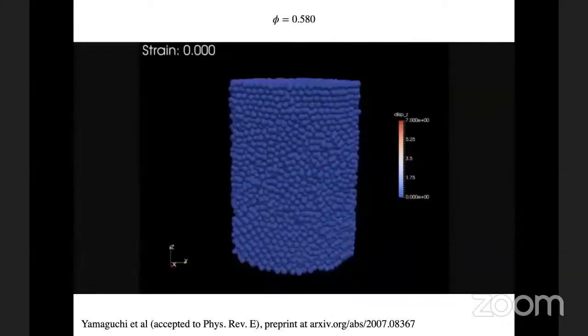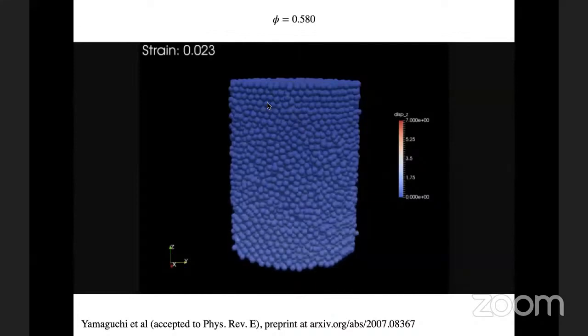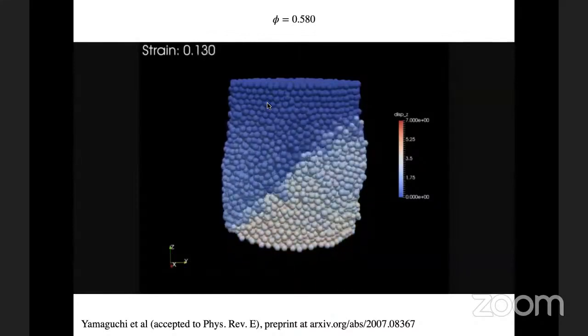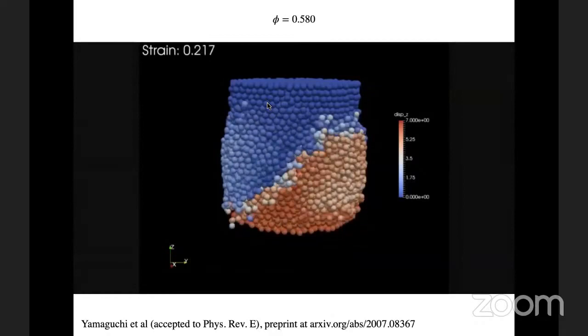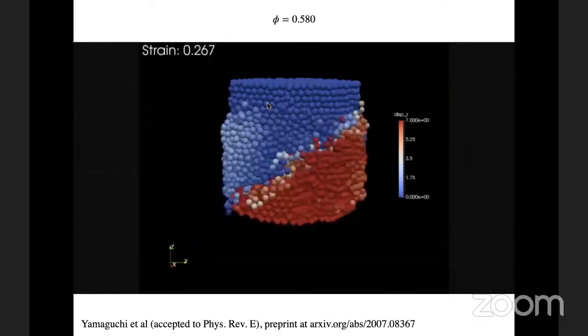So we can take these simulations. This is one at a high volume fraction, so that it's crystallized a little bit near the boundaries, and we can compress those. And they will fail like the experiments do by shear failure, shear band formation.